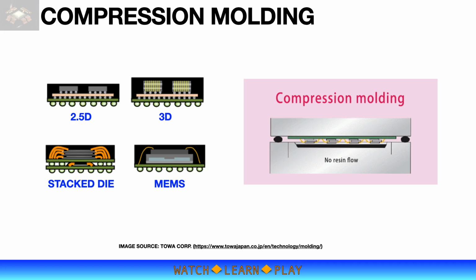Advanced packages such as 2.5D and 3D have critical requirements that are not possible with transfer molding without risking catastrophic device failure. 2.5D and 3D packages require stacking or multi-stacking of thin silicon chips, fine pitch mini bumps per flip chip, or long span of fine wire diameter for bonding to be packed inside the thin package within a limited space. The limited space constrains the resin flow, while long wire span of small wire diameter is prone to wire sweep due to transfer pressure, and thin dies may crack with mold packing pressure.